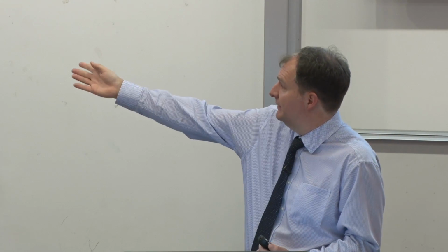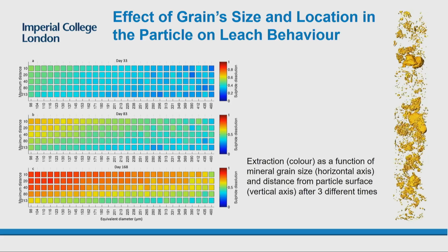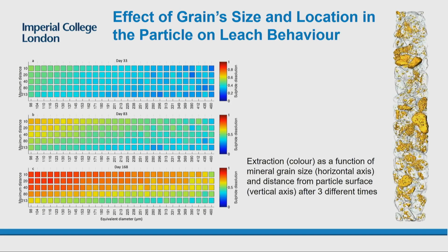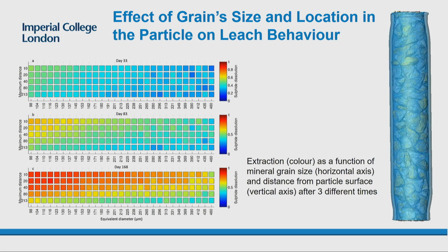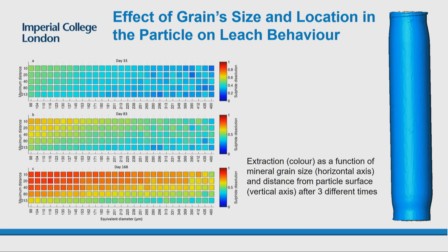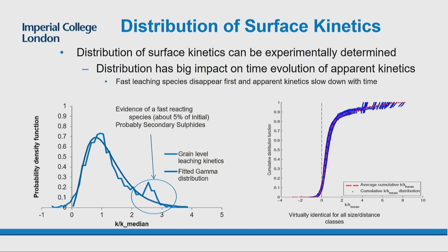If you look at the bottom there, after nearly 170 days, the stuff near the surface, small grains near the surface, are virtually completely leached, whereas the stuff, large grains in the middle, maybe only 40% of them leached. We could also, because we've got this giant amount of data, look at individual ones of these categories and look at the variability inside them. And so this says something about the variability associated with the mineralogy particularly and the mineral associations. And so you can tell the range of leaching rates.